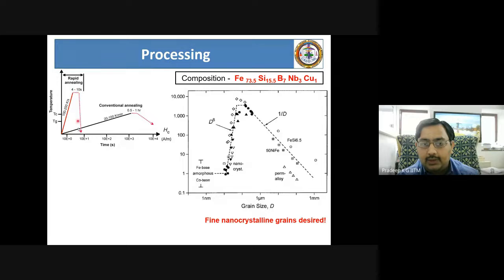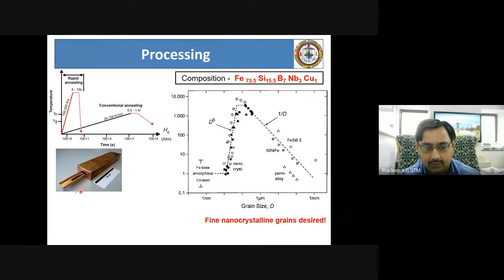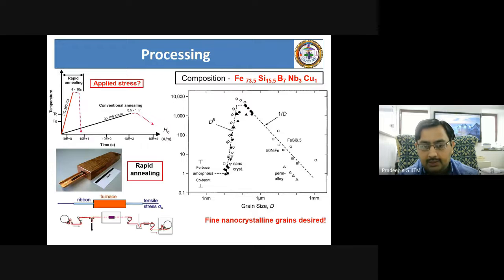And because these materials can be in the form of thin ribbons, as what you see here, this is the thin ribbon metallic material that we can produce, and you cool it very fast so that you are able to retain, or you are able to nucleate only nanoscale grains out of this material. Now this has all been standardized into an industrial practice, and these days you can see these kinds of materials being produced by rapid annealing in the presence of stress in a continuous ribbon to ribbon or reel to reel type of a systematic process.